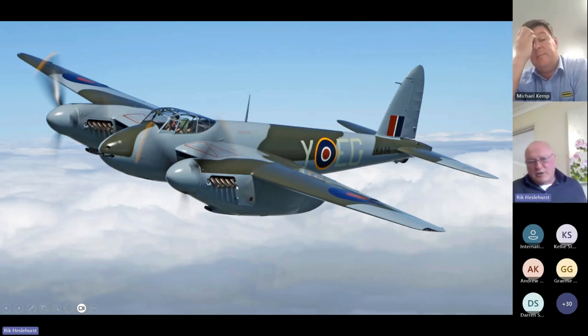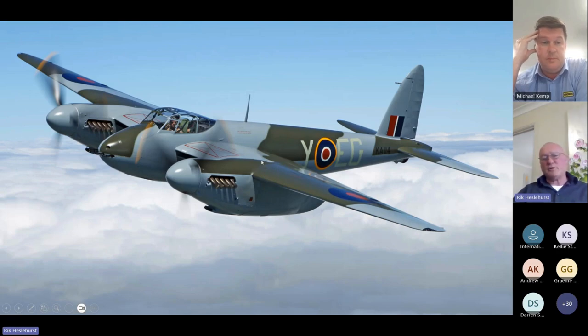Now, this is a de Havilland DH98 Mosquito fighter bomber called the Wooden Wonder. It was made of plywood and balsa core. And in particular in the fuselage, when the rudder is depressed, the center of force sits up high, which is going to cause a rotation of the tail cone or the fuselage. And to stop that rotation, which is torque, the plywood was placed at 57 degrees based on the load cases, but 57 degrees to overcome torsional deformation of the empennage. It works. It's been working for a long time.